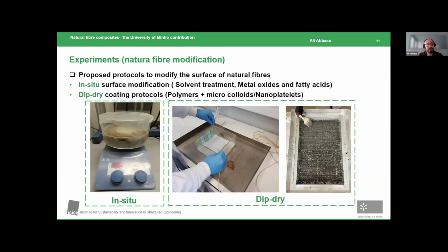So at the end, after trial and error of hundreds of samples and tens of protocols, we settled on two main protocols. The first one is called in situ. What an in situ surface modification protocol is, technically, you put in one pot the reagents of the coating itself, and you put the substrate, I'm referring to the natural fiber lignocellulosic substrate in this case, and you let it grow over time. Then you take it from this container and you treat it, and you have your fibers coated and ready.